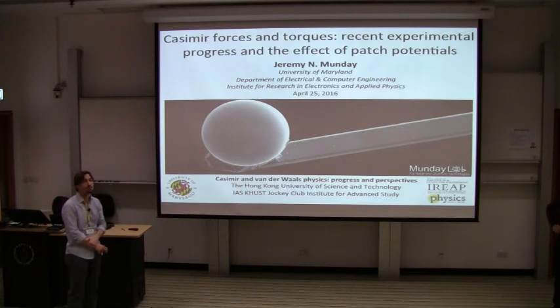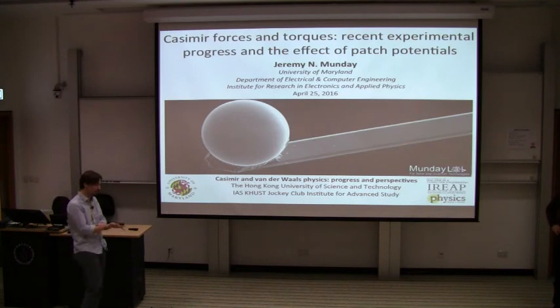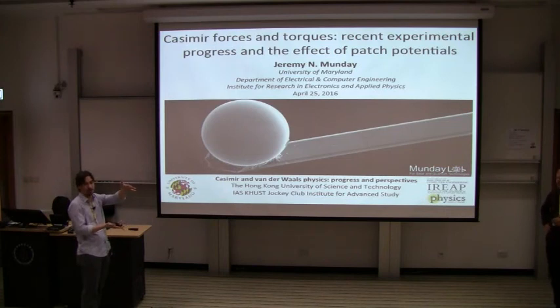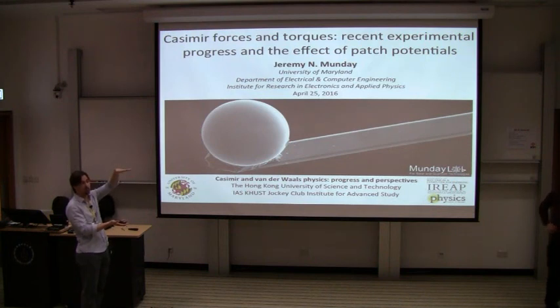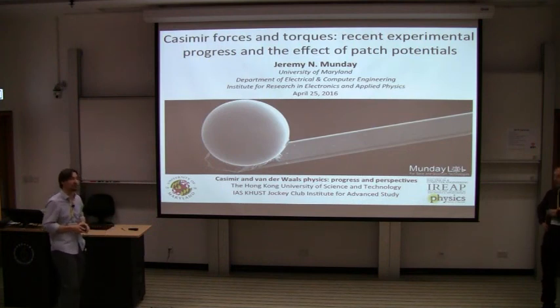So they have to be aligned somehow? Yeah, we have one surface where we align them, and the other surface has no alignment unless we have a strong torque or something like that. The idea is that you align them on one surface, and then they basically stay aligned, and we've seen that happen. The question is, if you bring in something that could cause the alignment to change, due to a torque, does the crystal rotate to find some new alignment? But it basically stays in plane. There's a lot of surface preparation you have to do in order to make that happen.